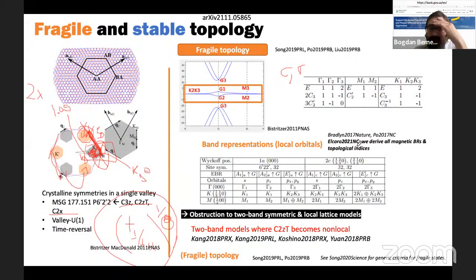So in this model, we can now look at the flat bands and describe them by eigenvalues of these symmetries, which are C3z, C2x, etc., and C2T, which basically complex conjugates eigenvalues. And the eigenvalues of these symmetries are such that these bands have the following eigenvalues, and you can prove this is true for any small angle. This is actually another beauty of this problem. It's not dependent on the model. You can actually prove that whatever model you have at a small angle, these are the eigenvalues of the Moiré bands in the Moiré-Brillouin zone. Now, why is this important?